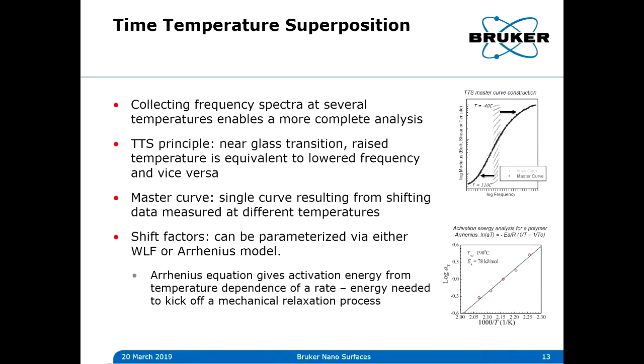Great. Okay, I'm going to talk a little bit more about what happens when you vary the temperature. I mentioned earlier that rheologists need the storage and loss modulus at both a range of frequencies and at variable temperature for a complete analysis. This is to allow the use of time temperature superposition in order to generate a master curve. So if you can collect the frequency spectra at several different temperatures, you get little curves like these. Each spectrum is shifted a little bit. Near the glass transition, raising the temperature is equivalent to lowering the frequency. So here we have some high temperature measurements down here, so they could be shifted over to the left in frequency, and the low temperature ones shift to the right in frequency.